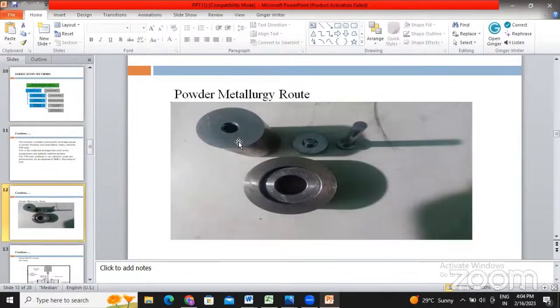That is our die for the powder metallurgy route. That is the upper punch, that is the lower punch, and that is the ejector. We fill the powder in that die after putting the lower punch inside it. Then we apply hydraulic pressure on the die, and the powder forms into a compact. That compact further goes for the sintering process, and after sintering, it goes for mechanical testing. That is the basic process for the powder metallurgy route. If you want to develop a composite through powder metallurgy, then we use that type of die.